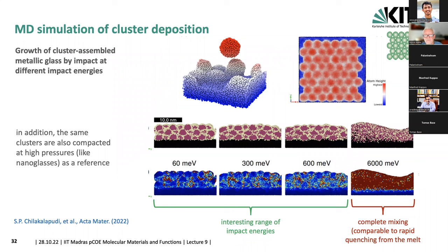Here you see how the clusters are deposited on the top with the red and yellow atoms. And at the bottom, you see the distribution of the potential energies of the atoms in the growing film. And you can clearly identify the interfacial regions for 60, 300, and 600 milliEV, where still the clusters or the interfaces are visible. So we can identify interfacial regions, and we can identify the cores of the former clusters. Whereas at 6,000 milliEV, everything is intermixed, and this would be really comparable to rapid quenching from the melt.